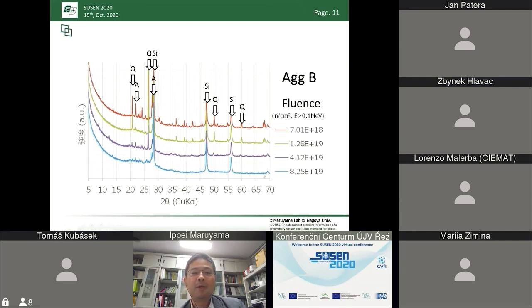And we also found that albite is a little bit more durable to the neutron irradiation, but still we see the reduction of the peak like this. So quartz and albite can be affected by the neutron, and they became amorphous. And if we closely look at this peak, we see some shift towards the smaller angles. It means that the lattice structure is a little bit enlarged due to the neutron irradiation. That is found based on X-ray analysis.